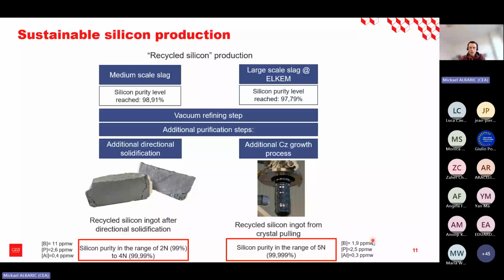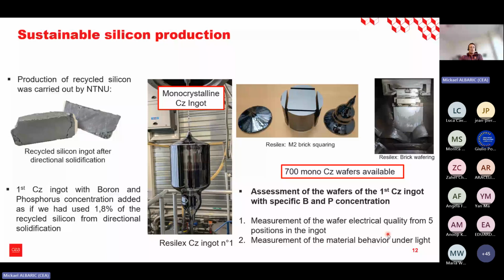So what we did, firstly, we used the recycled silicon after directional solidification production, and we first pulled a CZ ingot with boron and phosphorus concentration added in the feedstock, as if we had used more or less close to 2% of the recycled silicon from directional solidification. So we did this. You can see here the CZ ingot that has been pulled.